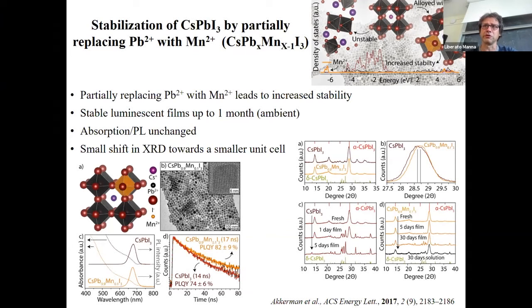So for example, in this work of 2017, we alloyed, we replaced 10% of lead with manganese. Manganese has a smaller ionic radius than lead. This decreases the overall size of the cage and makes the cesium cation large enough to stabilize this new cage. Because the overall reason for this transition from the perovskite to the non-perovskite phase is that the lead iodide cage is too large for the cesium to stabilize it. So either you alloy cesium with other larger A cations, for example methylammonium, or you reduce the size of the cage by alloying lead with manganese, and this is what we did.